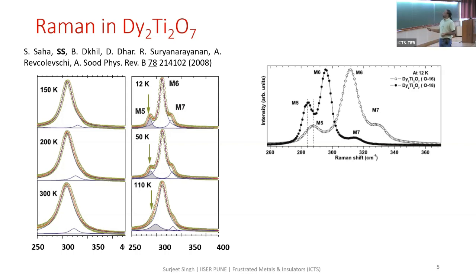We see that both M5 as well as the principal mode, which was already there, have shifted. This one is data for O16, and here's the data for O18. Both of them have shifted, and not only shifted, even the FWHM has decreased. Since the full width at half maximum scales inversely with the mass of the vibrating atom, it clearly indicates that this mode has to do with the phonons and not the crystal field.